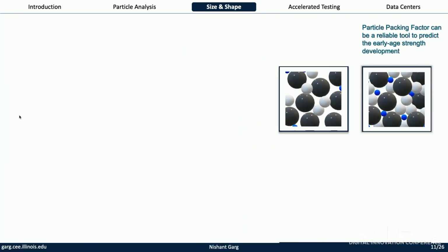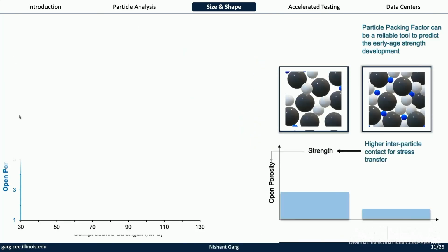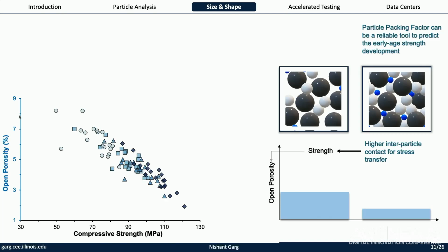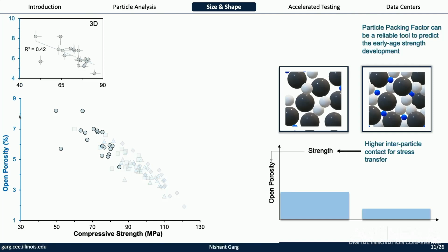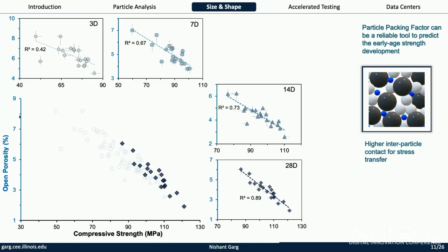Finally, the third thing is the durability, which we measure with porosity. And there also, we see a very nice correlation between the open porosity and the strength. So you get to lower porosity values and very, very high strength. So again, your typical concrete is around 30 megapascal. Your ultra high performance, you can go to 120 megapascal and has very low porosity, right? So very high durability, very long service life for your structures. And then if there's no steel in it, there's very less risk of corrosion. Okay. And again, you do this correlations, step by step, and you can see this.